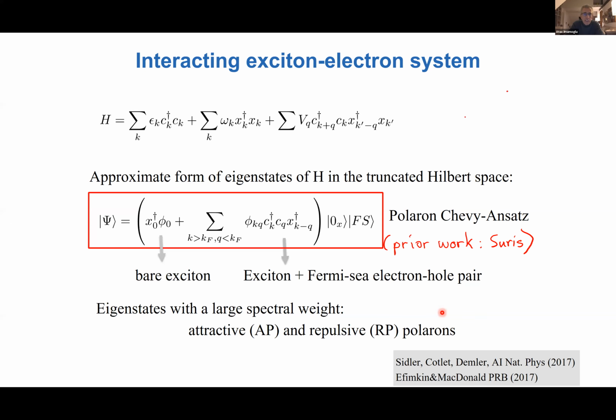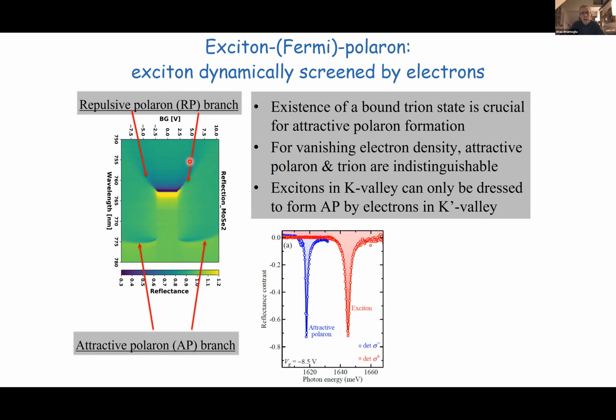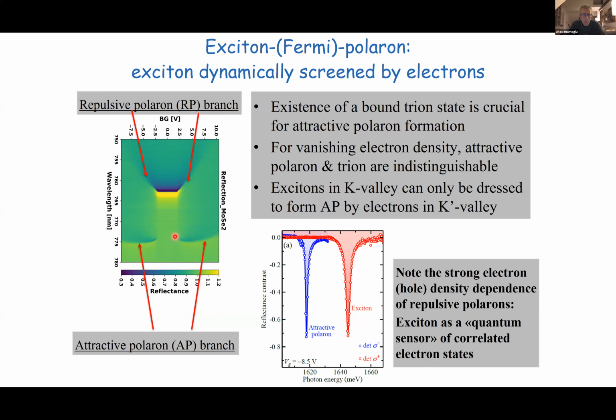What I would like to emphasize here is that, once we approximately solve the Hamiltonian, we find that the eigenstates with large spectral weight are the attractive and repulsive polarons. And these are the two branches that we see when we dope the system with electrons. So the exciton, as the system is doped with electrons, becomes the repulsive polaron, and then there is a new branch, the attractive polaron, which in the limit of vanishing density becomes essentially the trion. For the purposes of this talk, what is really important is this sensitivity of the exciton energy, or the polaron energy, on the electron density.